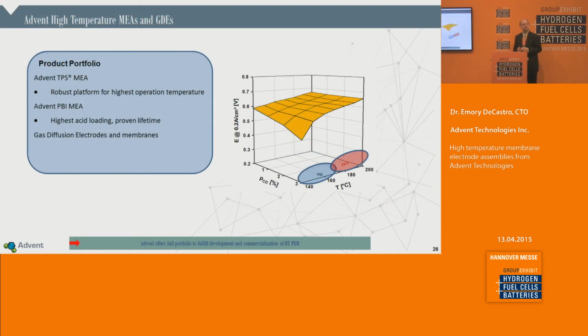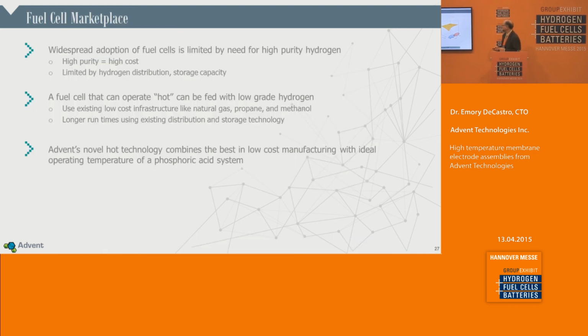So when we think about the Advent product portfolio, we really have two flavors of MEA, if you will. One is based on PBI, polybenzimidazole. The other is based on TPS. The TPS is a very robust platform, the highest operating temperature. PBI, certainly very high acid loading, proven lifetime. But we also now are selling gas diffusion electrodes because of our coating process, and standalone membranes too.